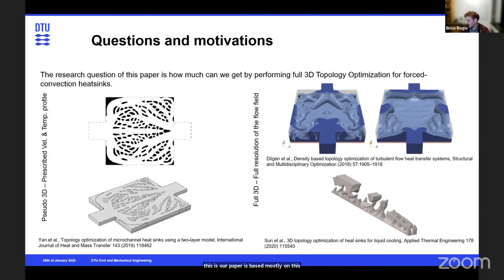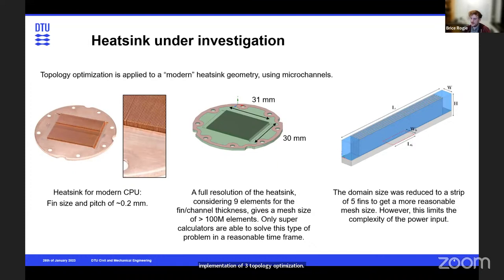So what kind of heat sink are we actually looking at? On the left, you see a picture of a real, what they call cold plate, which is used in your everyday PC. They are pretty simple. It's just straight fins, but the fin pitch and the channel size are pretty small, around 0.2 millimeters. If you want to model a whole heat sink, as an approximation, you need around 100 million elements to accurately discretize the fin and the channel size. And of course, not everyone can access a supercomputer that can go for 100 million elements and almost a billion degrees of freedom.